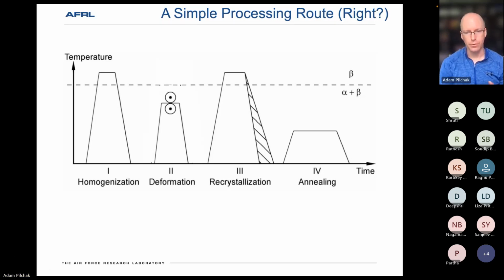But ultimately, because of the low thermal conductivity of titanium, you're generally limited by that thermal diffusivity, and so most components, at least within or greater than about 3/4 of an inch from the surface, end up forming these relatively large colony structures. And then finally goes through some low temperature annealing step just to relieve any residual stresses and things that might form.